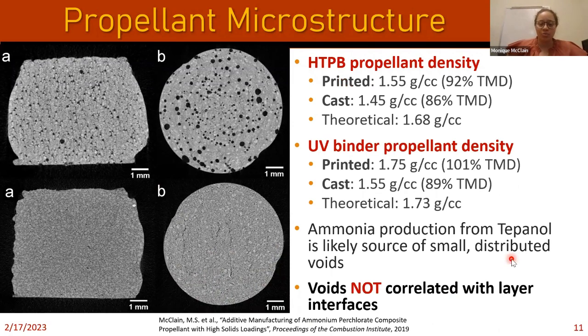When we're 3D printing or manufacturing propellants in general, we don't want unwarranted voids or delamination occurring because, again, that propellant is just going to burn much faster than it should. So we, of course, wanted to see what porosity our 3D printing process induced. So what we did was we took some micro CT scans of several different propellants.